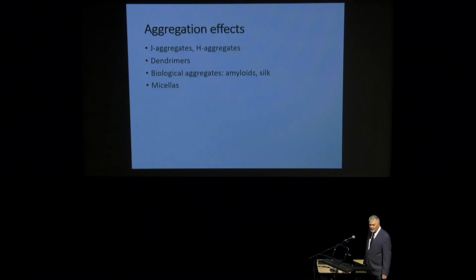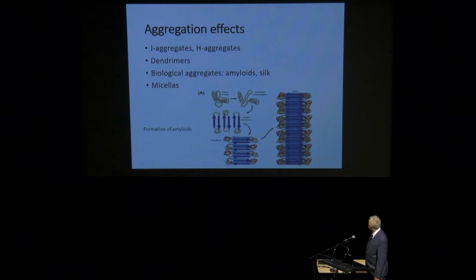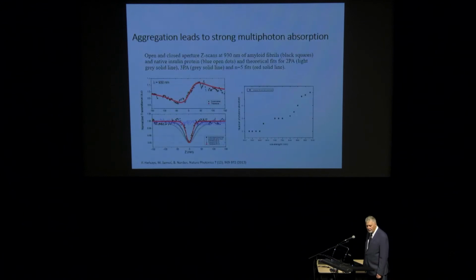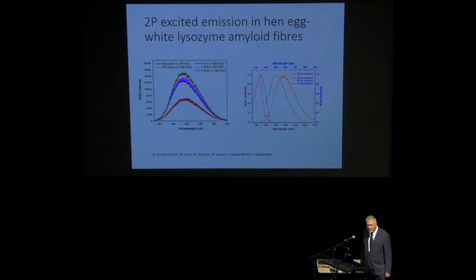So, aggregation effects. Aggregation effects can exist in many different systems. Dendrimers, micelles, J-aggregates, amyloids. Amyloids are very special proteins that are examples of very strong aggregation. And we found several years ago that compared to native proteins, they have orders and orders of magnitude stronger nonlinear optical properties. They are actually relatively strong nonlinear absorbers. They show 2-photon absorption, 3-photon, even up to 5-photon absorption under suitable light intensities. And this can be used, for example, for imaging amyloids in the presence of other forms of proteins.